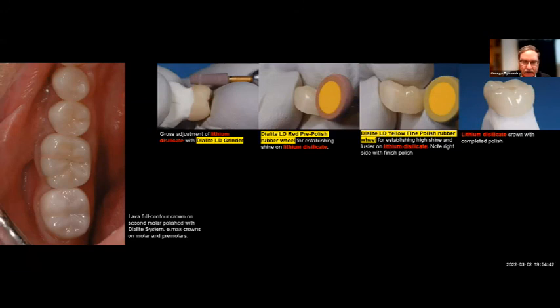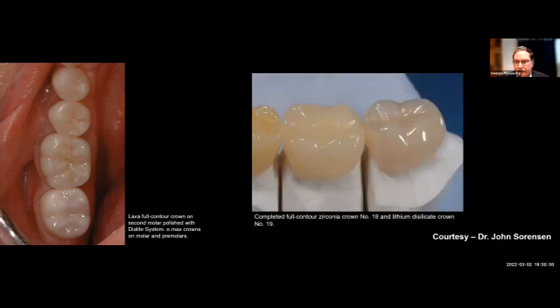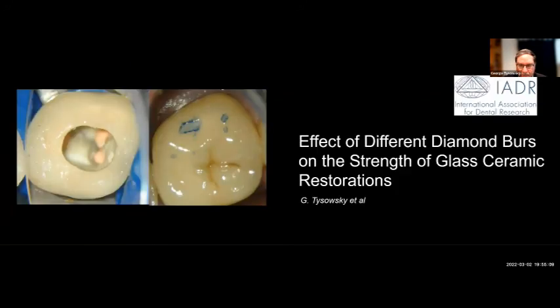Same thing on lithium disilicate. We use the grinder, the pre-polish wheel, the fines, and then create basically a beautiful crown. So it's very important to go back. If we adjust these restorations, use high speed, fine diamonds, copious water, and then make sure that we use the rubber assortments that we can to repolish these systems back in place. And this can show you, again, these are polished restorations, some of the beauty that can be achieved through these elements of application. The other factor we want to look at is what happens if we have to adjust or actually penetrate and do endo access.